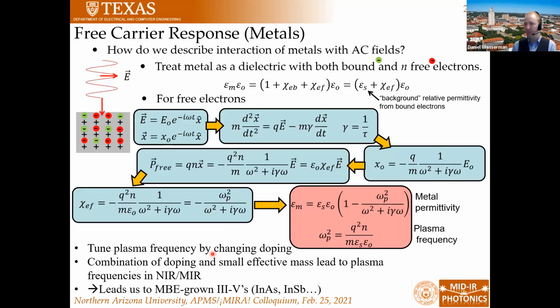But we can think about how we might engineer metals, right? If we go back and think from a fundamental point of view about how metals respond to incident light, we can treat the metal essentially as a dielectric with bound charge, some background permittivity, and a bunch of free charges that are sloshing around. Then we can simply apply Newton's equation of motion with the damping term and solve that. What we end up with is an expression for the displacement of your electrons, and then a polarization and an effective susceptibility, which we can convert into a permittivity. And this is nothing more than the Drude model for free carriers in a material.